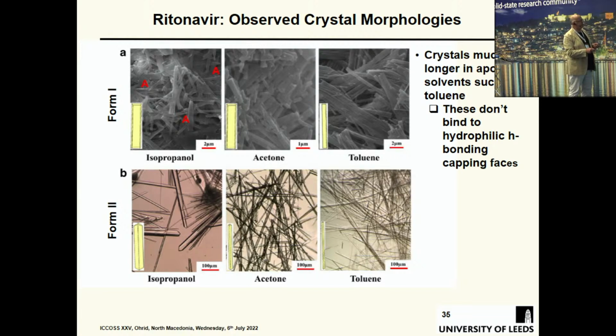Basically, three solvents. This is good standard solvent selection if you're doing it: choose a polar protic, a polar aprotic, and an apolar solvent, because that will enable you to see. Now, if you remember, the sides of the crystals are hydrophobic, the capping of the face is hydrophilic, so it's no surprise that if you crystallize it in toluene, for example, in both forms, they expand out. The toluene glues like hell to the sides of the crystal.